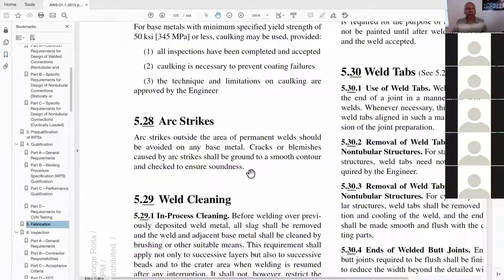Okay, so there's nothing strictly written in black and white about these things, but if you put 2 and 2 together, by default you're going to think, okay, I get it. We're going to allow the welder to use a grinder if he wants to, but we're not going to allow the welder to nick or gouge the base metal. The other thing we don't allow is, let's say they do a cap pass or a cover pass and it exceeded 1/8 inch of weld reinforcement. Well, they can remove it and re-weld it, but they cannot just fix it by grinding, because we have to be able to do a visual inspection on the as-welded test coupon. It can't be modified or repaired by grinding to pass a test, because what we joke about is we'll give that guy a grinder certification, but not a welder certification.